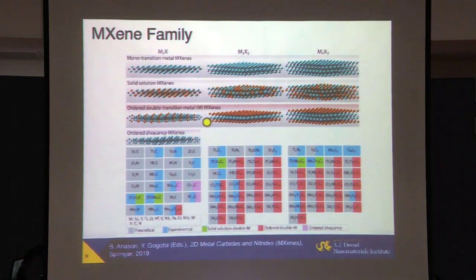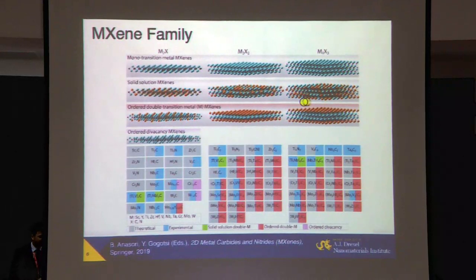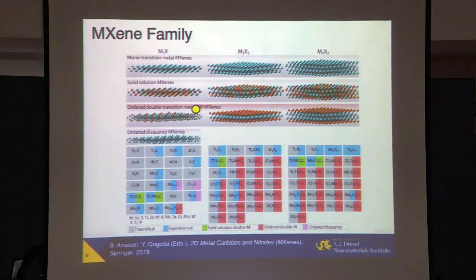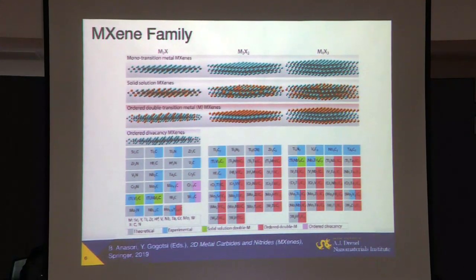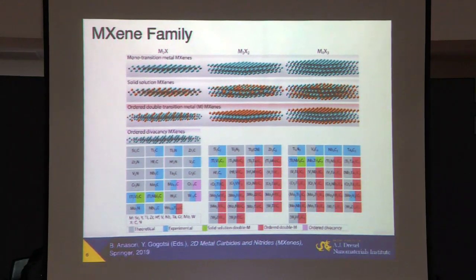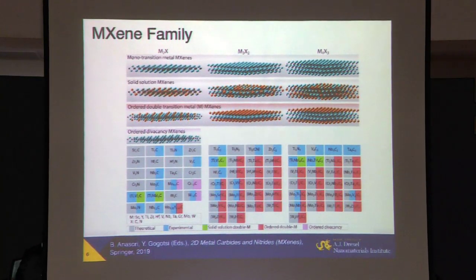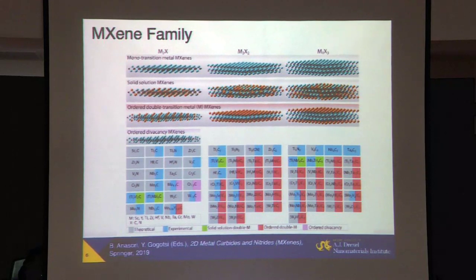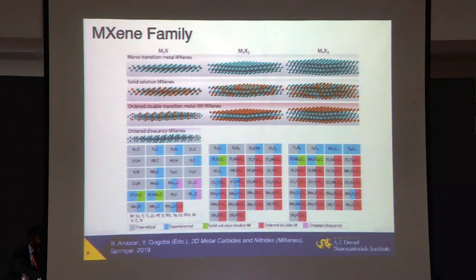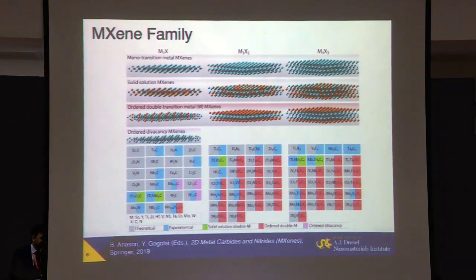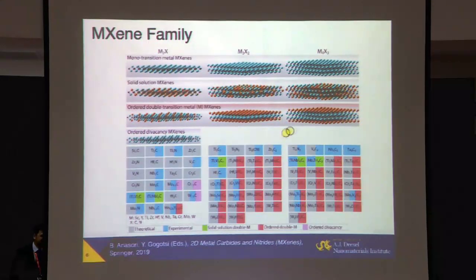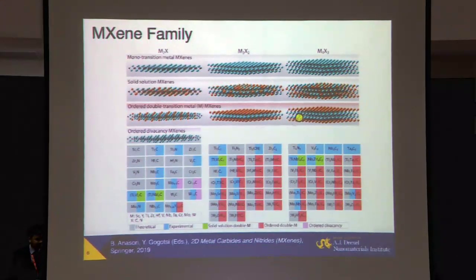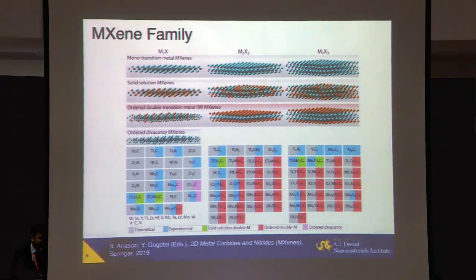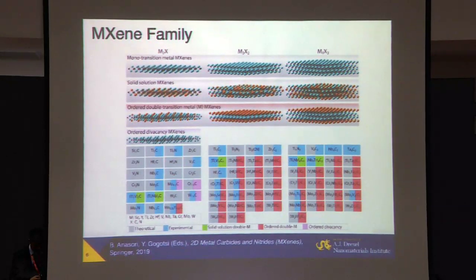But moreover, we can take atomistic design to the next level and make atomic sandwiches. One element, like molybdenum, is on the surface, and titanium is in the middle. So the surface element will largely determine the surface chemistry of the material, its catalytic properties, energy storage ability, sorption, and others. While the metal in the middle, which is a monolayer or double layer, will largely determine the electronic properties of this material. And this is not all.